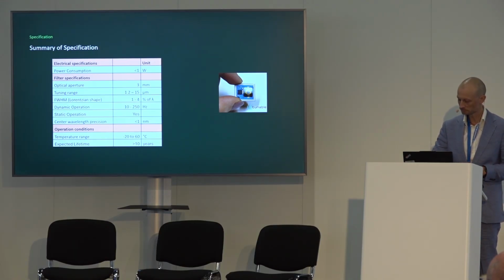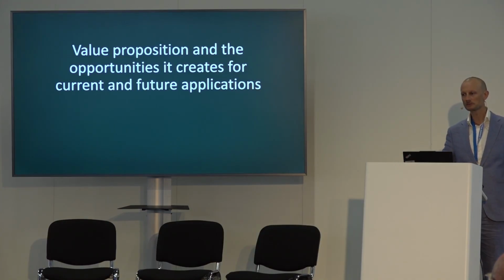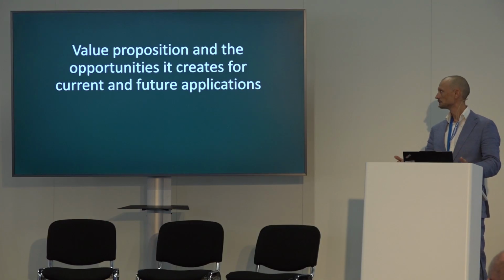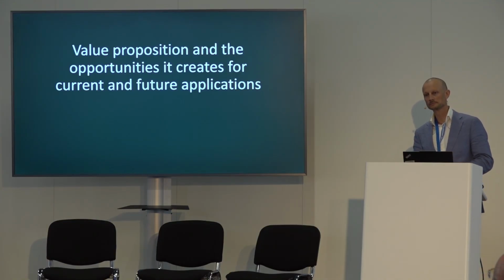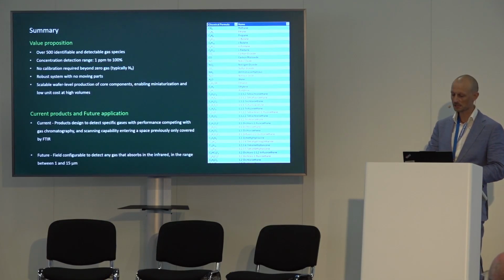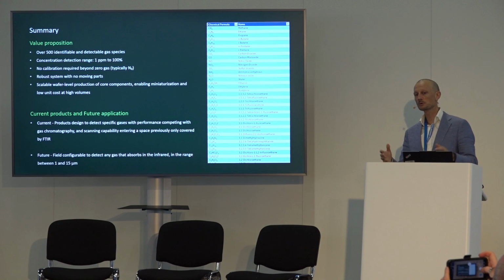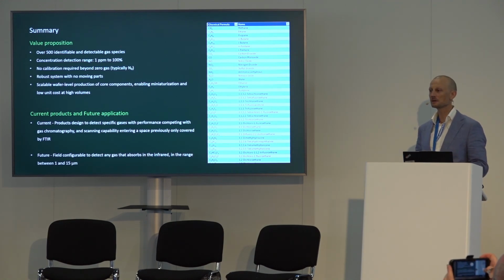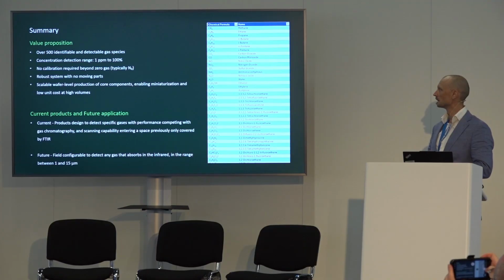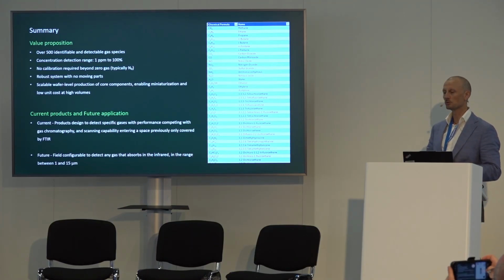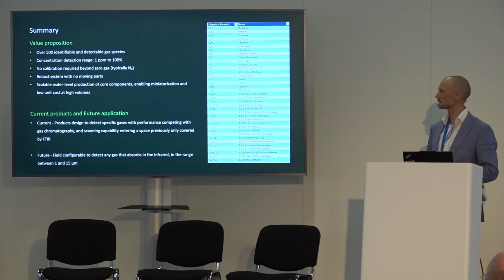Okay, so in summary, if we incorporate that filter into a testing scheme, currently being infrared spectroscopy, what that means is that we can detect, as far as we have identified, 500 different gases. Now, we can't detect all 500 gases at the same time. We can do about 8 at the same time. But we can do that with a detection range from 1 ppm to about 100%. We do use zero gas as a calibration, but we don't require any calibration gases in the field, except for nitrogen.